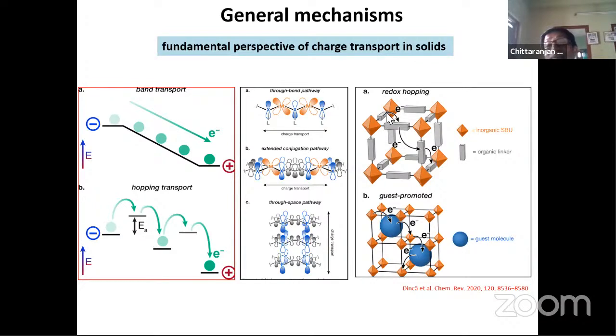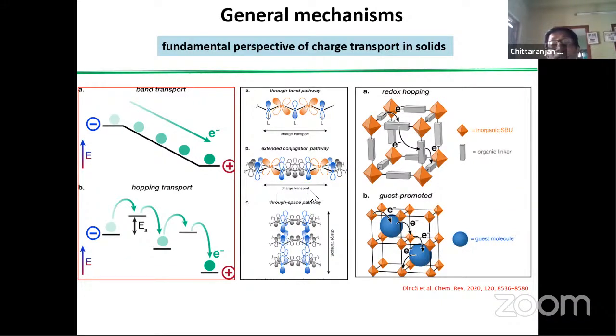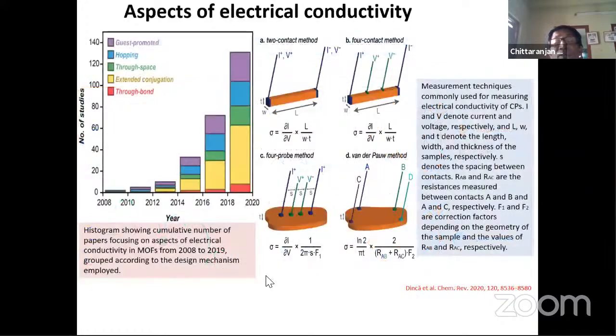Besides that, this bridging group, if the bridging group is redox active, then this group may participate in the charge transportation, not through bond, but through space. So through bond, through space, charge transportation may be responsible for the higher conductivity of this type of materials. And in metal organic framework, the structural strain over this transportation process is observed, and the conductivity is enormously changed.